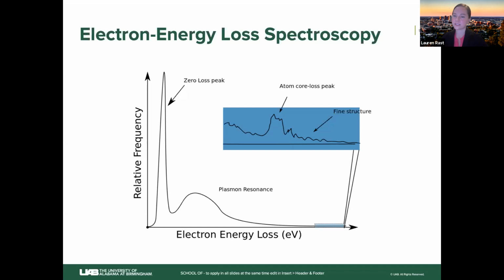We have devices like a transmission electron microscope that works with electron energy loss spectroscopy, and it can provide structural and chemical information about different samples. With this type of measurement, we can even go down to atomic resolution of a sample. Okay, so we have an idealized generic spectra here. On the left, that's a zero loss peak for elastic collisions. That's not going to be included in the model spectra, but we have a plasmon resonance there, and that looks like a bulk plasmon resonance. So we have a broad peak that's shown in this model spectra.